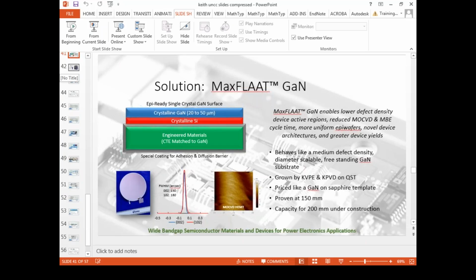And it had narrower X-ray line widths than we'd ever had on the thousands and thousands of GaN on sapphire wafers we grew. It's not quite as good as GaN on GaN, but it's much better than the GaN on sapphire. And we were really surprised because it's got silicon in there. We've always treated silicon as like the enemy, but that's if it's a bulk silicon layer. But this is a thin silicon layer. So this stuff's looking pretty hot to us. And so we gave it a name, and we're marketing these, we're calling them evaluation materials.